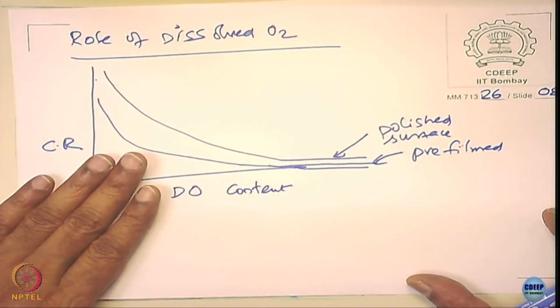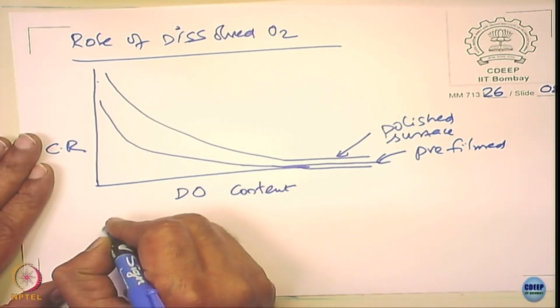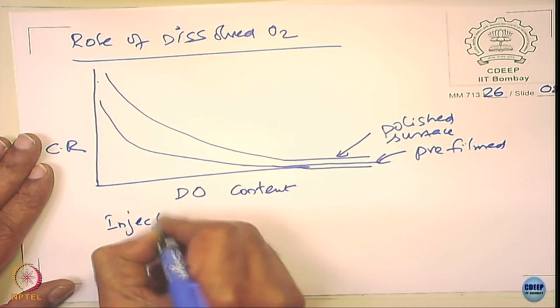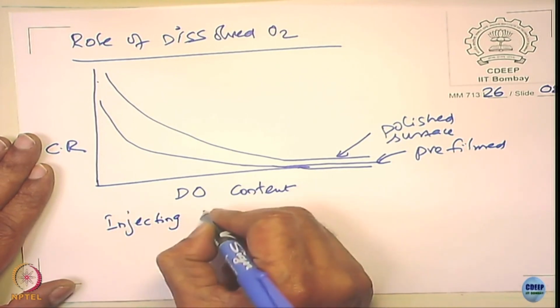It is very similar to critical current density, right? When you reach the critical current density, at that point of time, you have more metallic ions, then the passive film starts forming. So, you need a critical amount of metal ion concentration on the surface in order to form the protective oxide film. So, the oxygen content, it does help to do this. This means, it is very interesting here, the corrosion control in this case is done by injecting some oxygen content.